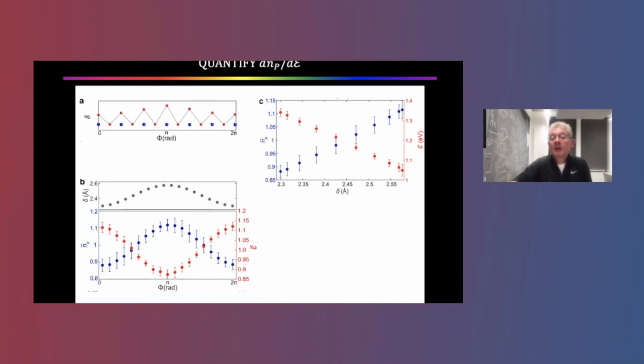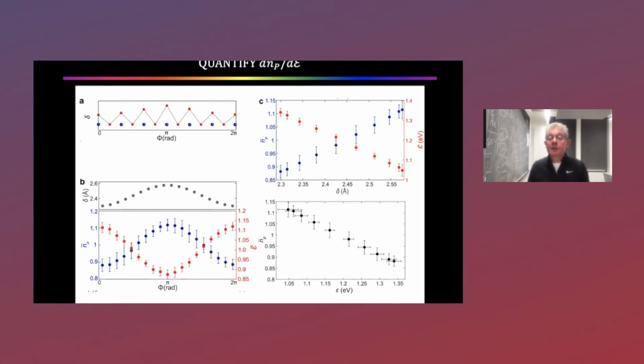All right. Now we can quantify the rate of change of electron-pair condensed pair density with charge transfer energy by removing the common variable, which is phase. And here's the key result of the experiment. You can alter the condensate pair density by almost 25% in BSCCO by altering the charge transfer energy by almost 30% in BSCCO. This is a fact, okay? Independent of theory, this is a striking fact that you alter the strength of the superconductivity by dialing the charge transfer energy.